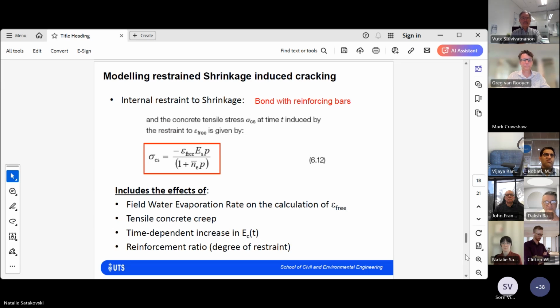As I said, concrete creep in tension is extremely important, so that's included as well. We have developed tensile concrete creep models that include the effect of fly ash and slag, so I'm pretty confident with this one. The time-dependent increase of the elastic modulus of concrete is very important. And finally, that's more the structural design: the reinforcement ratio is governing the degree of restraint. So that's all that needs to be included in that modeling.